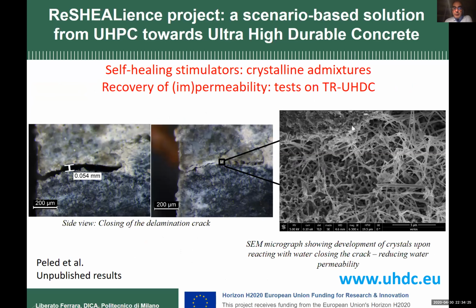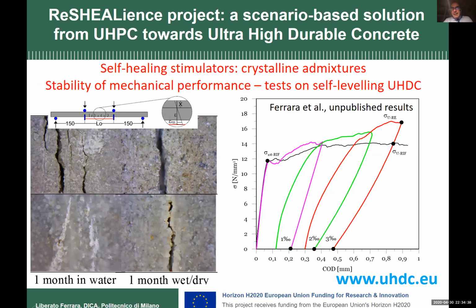We also observed, in other images of the cracks closing, how under repeated cracking and healing cycles — shown in this graph with the purple, green, and red curves — every time we pre-cracked the specimen, we healed it for 1 month. When we restarted, the material was able to repeatedly guarantee the same level of performance.